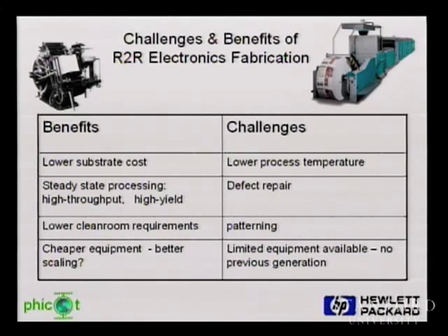The reasons why you might want to go to it, basically, it's really about cost, and in many different aspects, and we'll be talking about all those. Certainly the fact that plastic is cheaper than glass, being that if nothing else, it's 40% of the weight for the same area. That's important because it's maybe 50 microns instead of half a millimeter, and it's much less dense. And to first order, everything else in your manufacturing process is going to scale with that. So at the end of the day, you have a pretty big fundamental advantage.